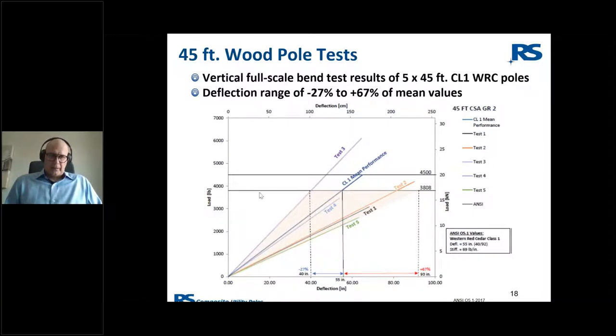If you look on the graph there, you can see that the blue line, if you will, represents class one mean wood pole performance. Test three on the left of the 45 foot class one wood poles has tested the best. It is not only the stiffest, deflecting about 40 inches at its factored class load, which is the 3,800 pounds. And by the way, this has been factored to CSA construction grade two. So that's a 0.85 factor on the 4,500 pounds of load, which brings us down to about 3,800 pounds. But you can see it broke probably at around 6,000 pounds, it looks there.